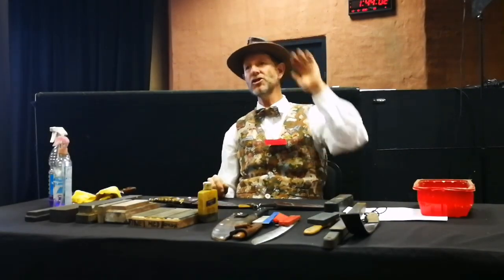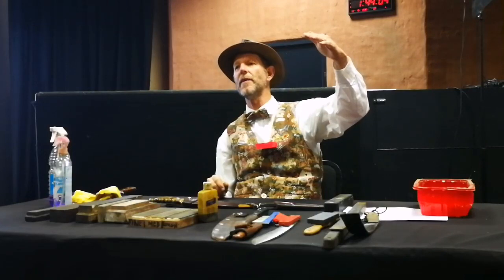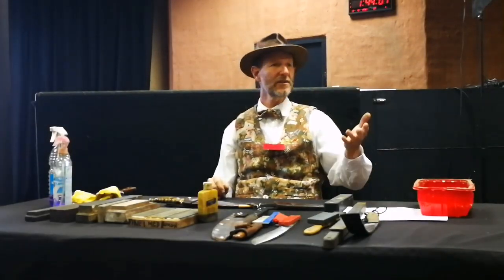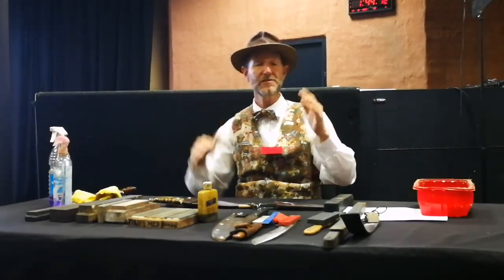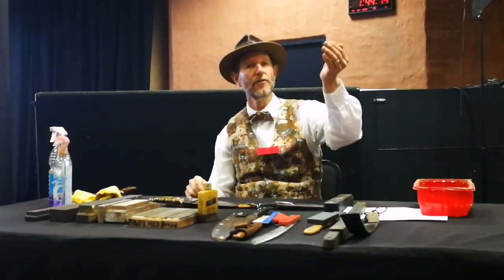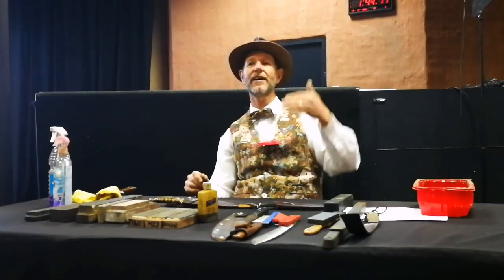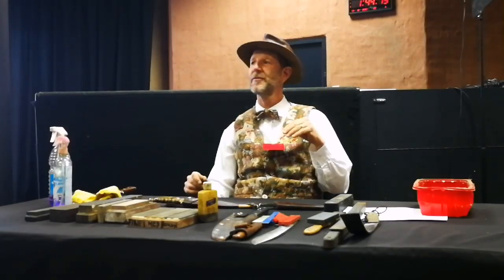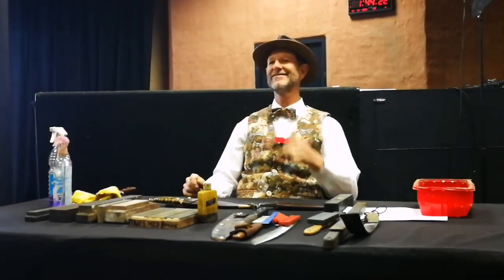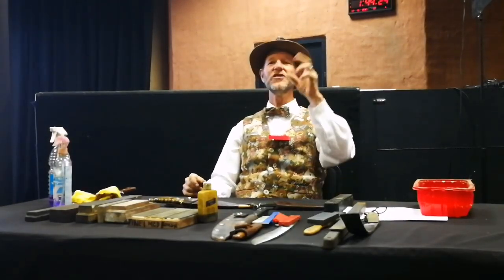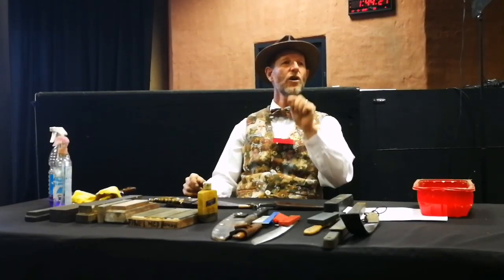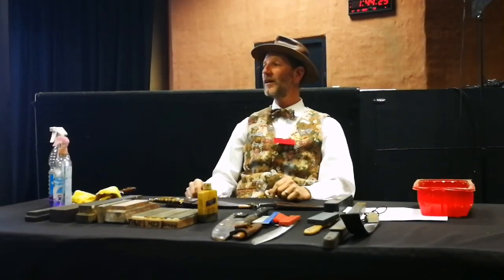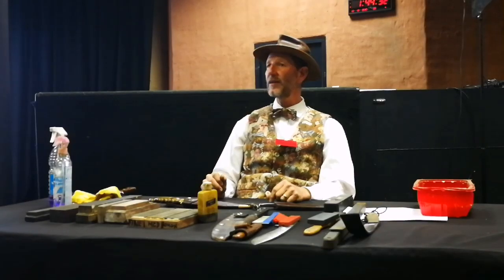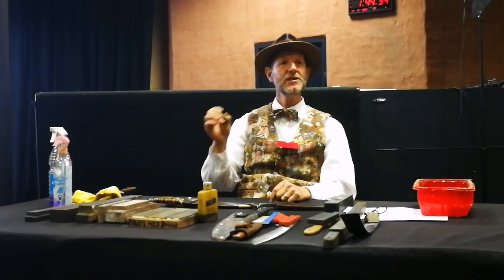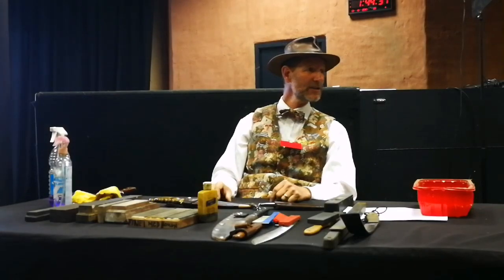Okay, so you have overshot the required hardness by a certain amount. By tempering in an oven, and it's kitchen oven temperatures, 200 degrees, thereabouts. It does vary. But through tempering, you now reduce that hardness and you come back to the hardness you desire, the Rockwell hardness. The scale Rockwell, in particular Rockwell C, is how we measure hardness on knife blades.